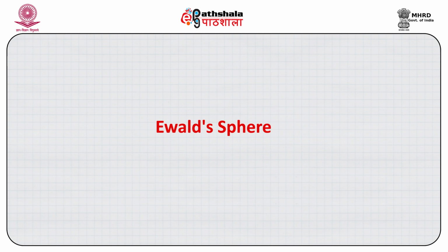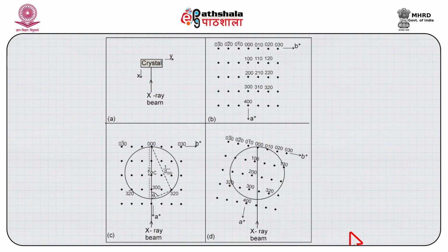In this we will look at the real lattice and the reciprocal lattice. Now, in this diagram we have a sphere constructed which has the diameter 2 by lambda. Remember, lambda represents the monochromatic X-ray which we are using to investigate the crystalline material. Now, if we have an X-ray of 2 by lambda diameter circle, then the Bragg's equation is satisfied in this diagram by 1 by d